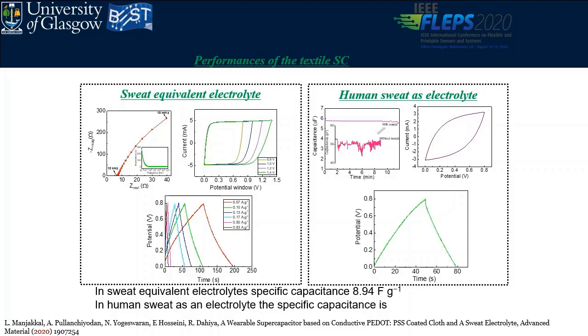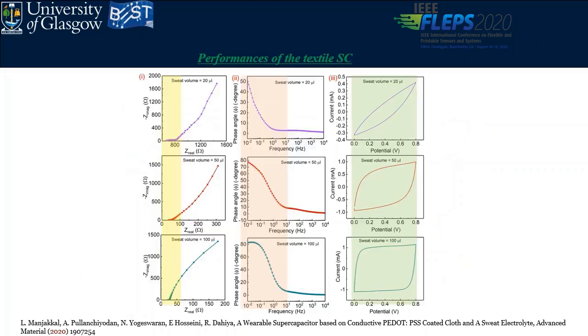When I compared the performance, I noted that in both devices the performance is almost the same, at 8.94 farad per gram. And here I did an analysis with a different volume of sweat, to see the influence of different volumes of sweat on the electrochemical performance.